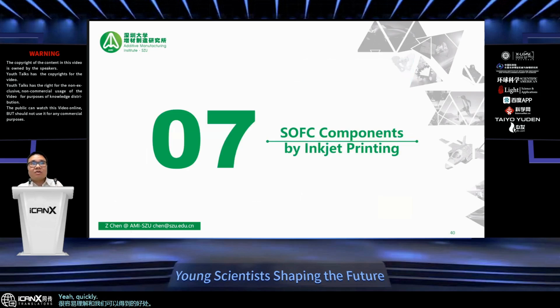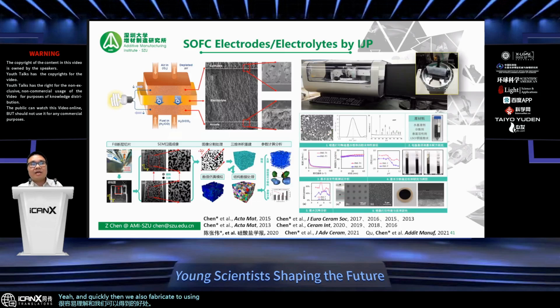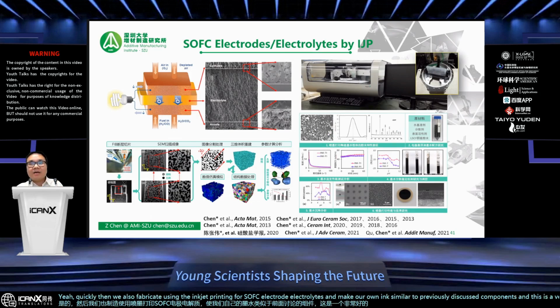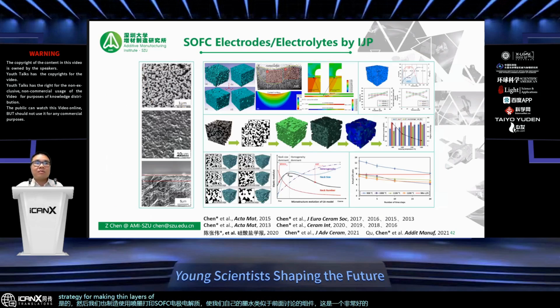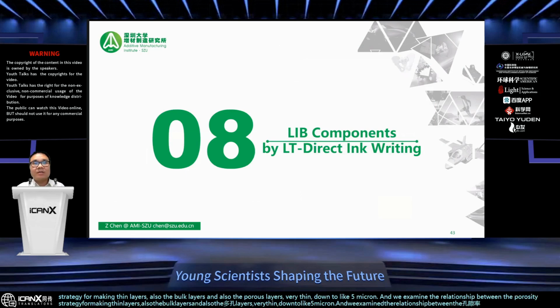Yeah, quickly then, we also fabricate using inkjet printing for SOFC electrodes and electrolytes, and make our own ink similar to previously discussed components. This is a very good strategy for making thin layers, also bulk layers, and also porous layers, very thin, down to like 5 micron. And we examine the relationship between the porosity and the mechanical performance.